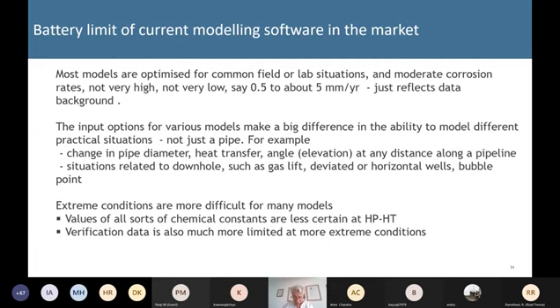Some of them are better at handling the elevation profile of pipelines, or actually looking at the wells and looking at bubble point, the impact of secondary recovery and that sort of thing. These are not very well covered by the majority of software. And they also tend to be limited in the high pressures and high temperatures you can go to. And you have to bear in mind that we depend upon physical and chemical constants in various places, and they're just not known. They're just not available for some of the more extreme conditions that we deal with in, for example, injected gas systems, which can be ultra high pressure, and we have to be aware of the limitations of the models.